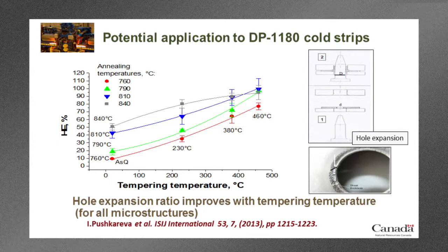Dual-phase steels are very good in terms of strength and ductility, but they have one drawback, especially when you get to high-strength dual-phase steels, is that their damage resistance is actually quite low. What's happening is that because you have these two very dissimilar phases, the ferrite and the martensite phase, when you strain the material, there is a strain partitioning effect. The martensite will not deform very much, and the ferrite wants to deform a lot more. So at the interface between the two, you can nucleate voids very quickly, and those voids can grow to become cracks, and essentially the material will fail at a very early stage of deformation.